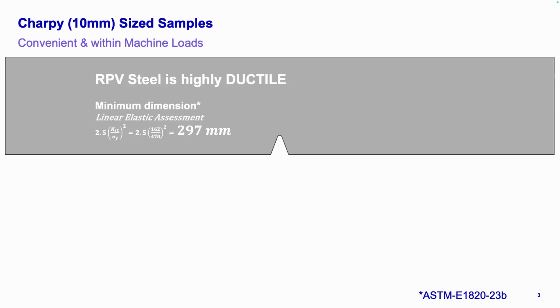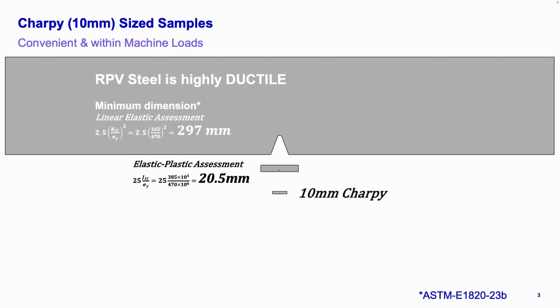If I talk about linear elastic approaches and I look at the typical standards for fracture toughness assessment, if I want to use linear assessments, I would have to have a very large sample. Difficult to test, very high levels of load required, and I can't put that in a Charpy testing machine. If I go to elastic-plastic assessment, the J-integral method, for looking at my fracture toughness, much better for my sort of material. This is an incredibly ductile material. And I get to an approximate sort of sizing that I'd need there to be more reasonable, but still not quite a Charpy.